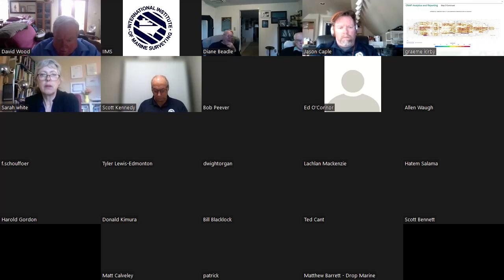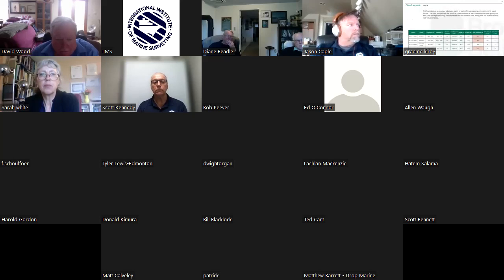We of course give the overhaul team and all of our clients a tabulated breakdown of the data as well. So we take all of the data sets, and for each scan zone, one by one, we apply our algorithm to it, and it extracts the various data and gives us plate section summaries. And for each category, which you can see in the 5 view that you saw previously, you'll have individual tabulated defect reports. So it'll show you the total test area in millimeters squared, the average wall thickness for that plate.